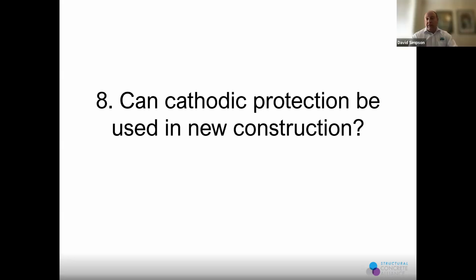No, I think there are huge benefits of using cathodic protection from day one instead of turning it on once the system started corroding. Because as you've mentioned before, Chris, for me, it's that buildup of alkalinity, which is the natural barrier to corrosion. So we always talk about the chloride to hydroxide ratio in terms of the initiation of corrosion. So anything that you can do to build hydroxyl ions and alkalinity at the interface between the steel and the concrete is always going to prolong the structure long term.